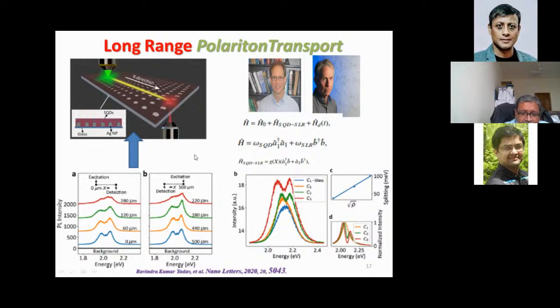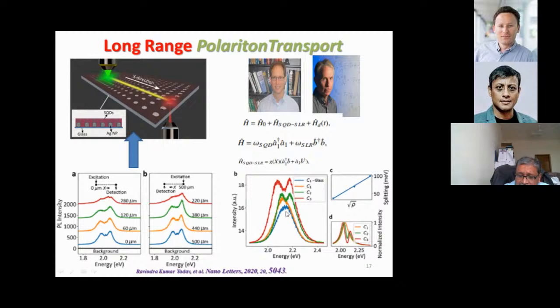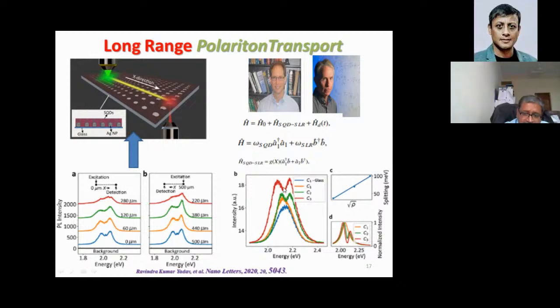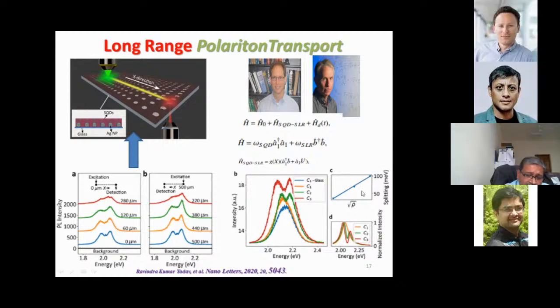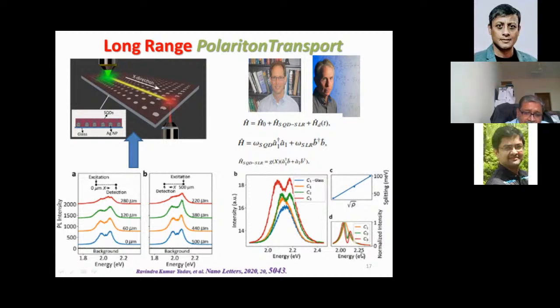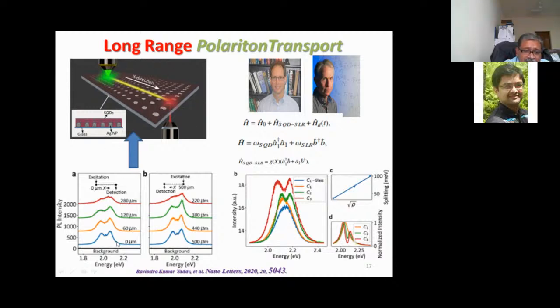So when we do that, what we observe is, of course, we see this kind of splitting as I mentioned earlier, and we see this scaling with square root of concentration. This is also modeled by a cavity QD model using this formalism here, including the QD and the lattice mode interaction for the Hamiltonian.